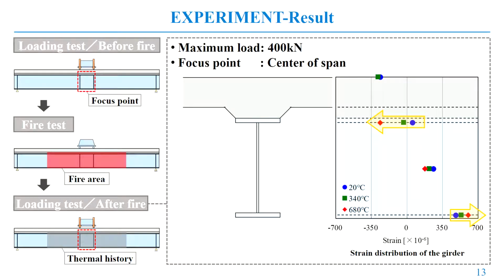This slide shows the results of static loading test after fire. As you can see, the strain distribution was almost the same as the room temperature at 340 degrees Celsius. On the other hand, the strain distribution was a tendency to approach non-composite behavior at 680 degrees Celsius because of the decrease in rigidity due to cracks that were generated in the concrete slab.